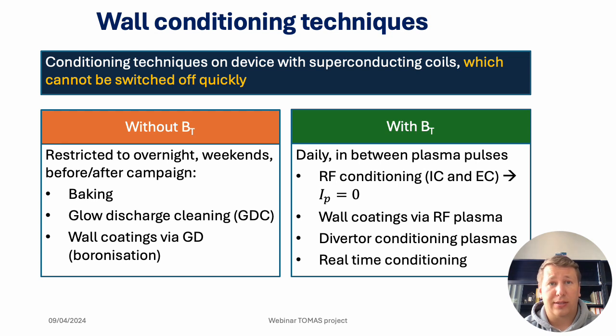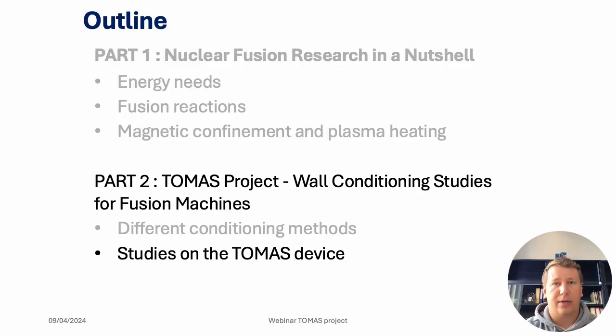In contrast, some techniques like radiofrequency plasma conditioning and wall coating via radiofrequency plasma must be applied while the magnetic field is on. Combining both types of wall conditioning concerning the experimental timeline leads to the most efficient cleaning result and better plasma performance. The wall conditioning techniques have to be individually optimized for each fusion device.